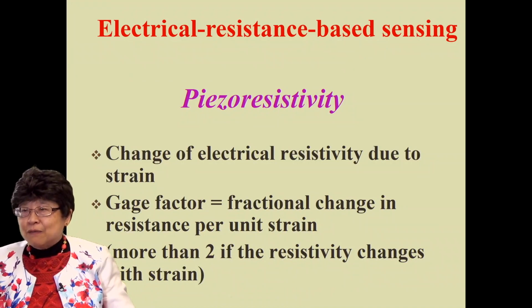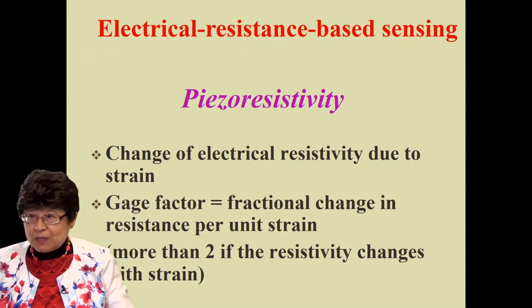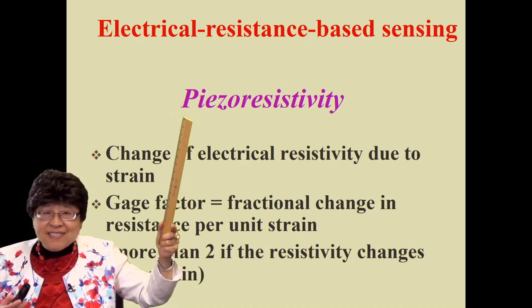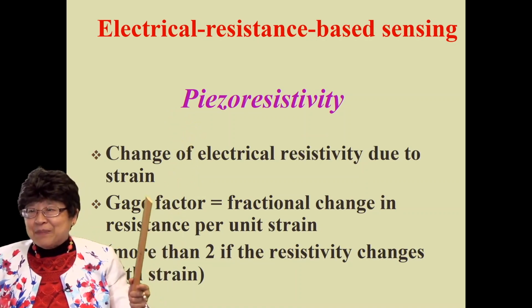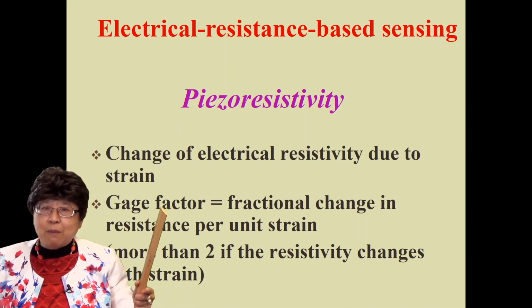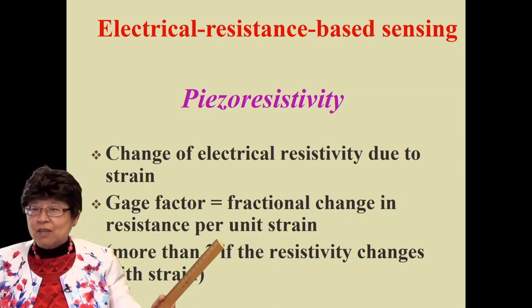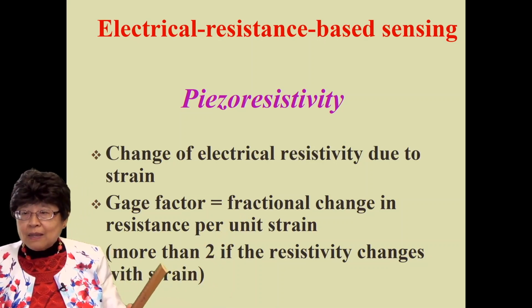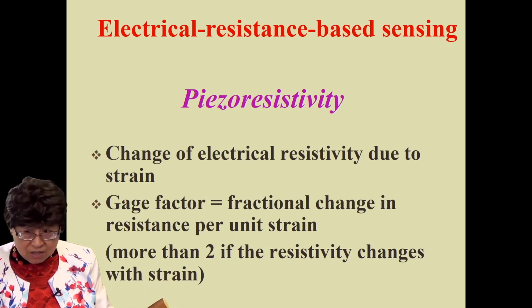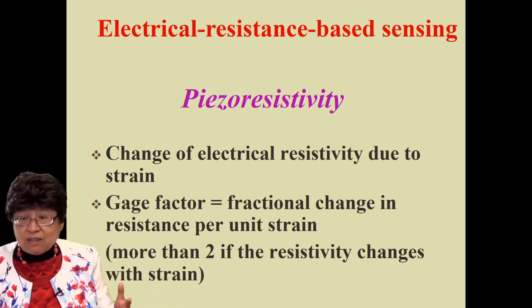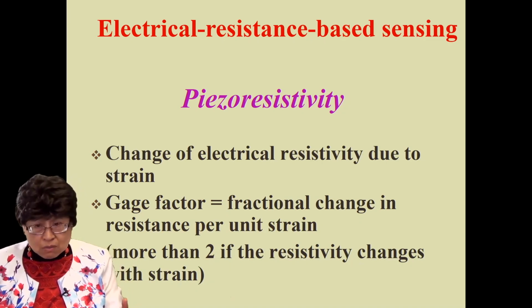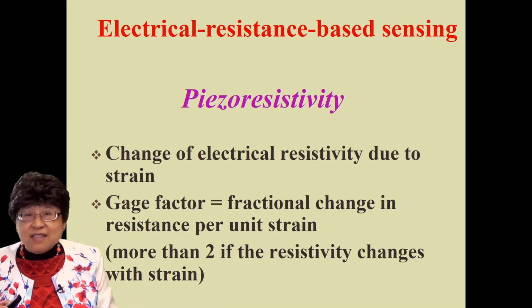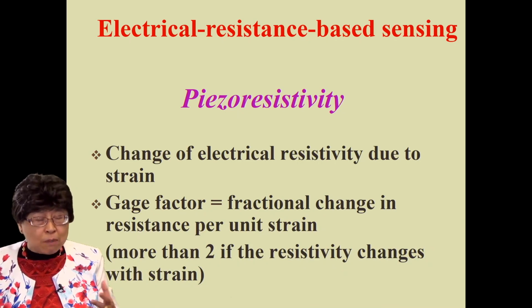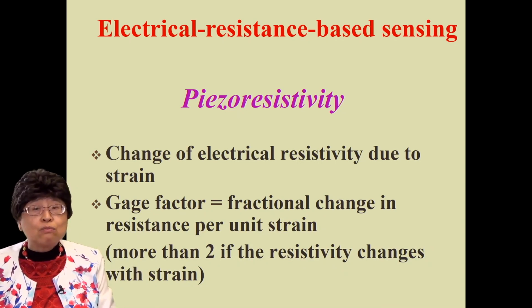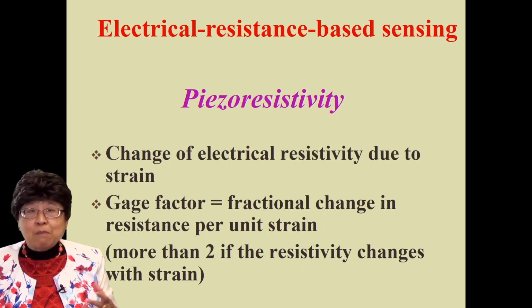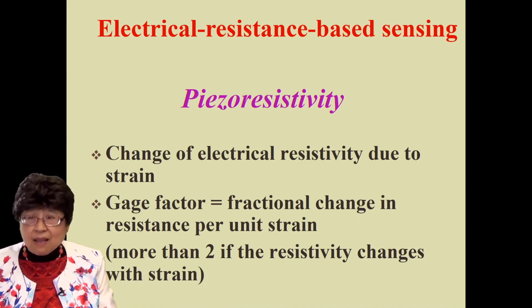The effect of stress or strain on the electrical resistivity of a material is known as piezoresistivity. This has nothing to do with piezoelectricity. The severity of the piezoresistivity is described by the gauge factor, which is defined as the fractional change in resistance per unit strain. If the resistivity doesn't change with the stress or strain, but just the dimensions change, then the gauge factor is typically 2 or less than 2, depending on the Poisson's ratio. But if the resistivity changes on top of the dimensions changing as you apply the stress or strain, then the gauge factor can exceed 2 greatly, even a few hundreds. And so the sensing becomes much more sensitive if you have the resistivity changing. That is piezoresistivity.